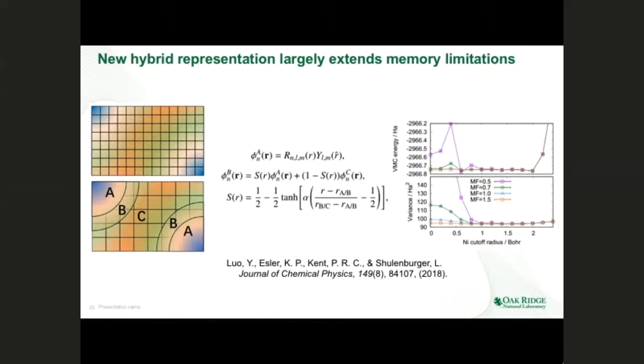Basically, we usually divide the real simulation cell into B-splines, the blips. But what we can do is divide the simulation cell into 3 regions, where the A region is the core, the C region is the intermediate, and the B region is the transition region between those two regions. This is kind of similar to an APW-like separation of the wave functions. If you look at the right, the MF stands for the mesh factor. The mesh factor defines how dense your wave function representation should be. And we are seeing that with a suitable cutoff radius